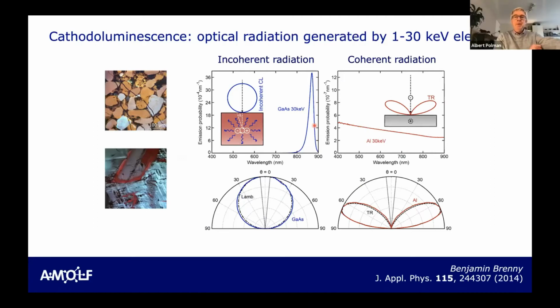So it's about cathodoluminescence. That's the radiation that is generated when an electron beam hits a surface. And that's a very old technique. I mean, geologists have done this since the 1970s. They take a piece of mineral and they like to know what it is. You put it in your SEM and then you can make your SE image, but also you can make a map of the radiation that comes out. Those are the two pictures on the left, and not from our group's work. This is from geology groups. They take a piece of calcite and the color reflects the color of the light coming out, and that's how you identify a mineral. Look at the scale bar. It's not so easy to see here. It's 100 micron. That's, of course, typical grain sizes that often play a role in geology.